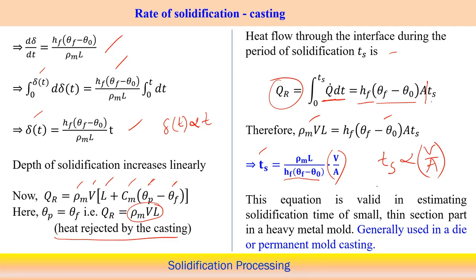So, again, to summarize: if it is a sand casting process, Ts is proportional to the volume by area squared, but if it is a permanent mold casting or die casting process, Ts is proportional to only the volume by area ratio. This equation is valid for the volume by area ratio when the solidification time is very small, for a very thin section part and a heavy metal mold.